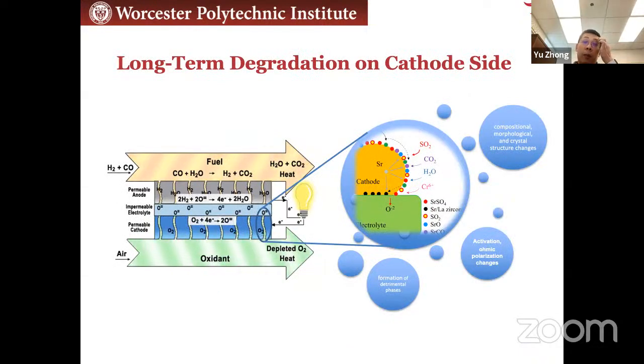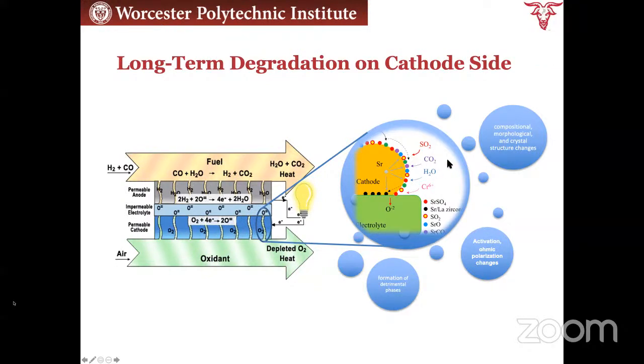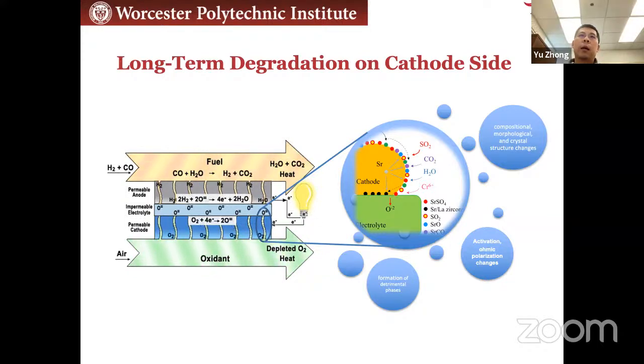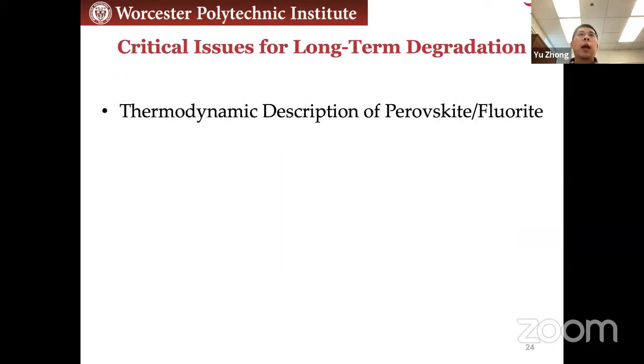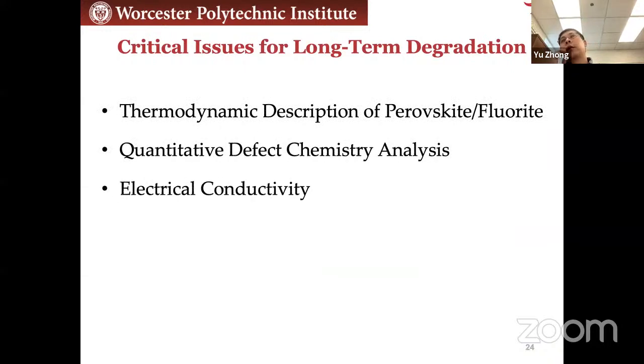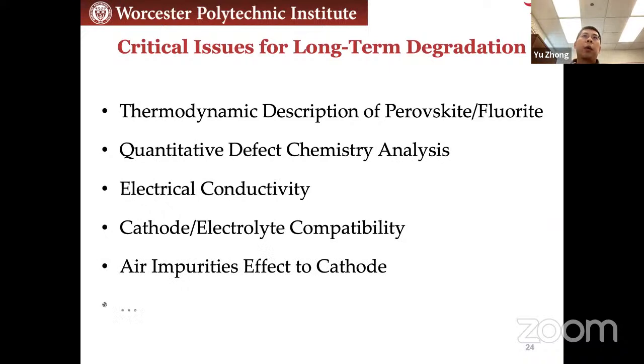But the problem for SOFC and later on for SOEC is the oxygen electrode, where people found a lot of degradation. For example, this is what's happening in SOFC. Your cathode can react with electrolytes. Your cathode will get in touch with air. In air, you have SO2, CO2, water vapor, chromium, all these things. All these impurities will attack your cathode material, and that will greatly reduce the performance. That is what we call long-term degradation. Your performance drops with operation time.